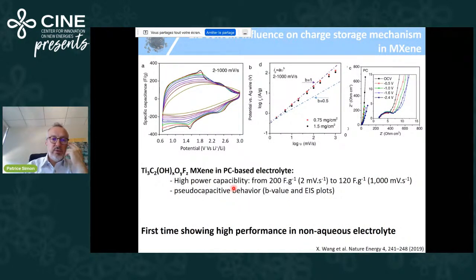And then if you go a bit further, you can see that you have very nice power performance up to 1 volt per second. The peak current changes with b equal to 1, which means that it changes linearly with the scan rate. It's non-diffusion limited. And finally, it was the first time that we showed high performance in non-aqueous electrolyte from MXene.